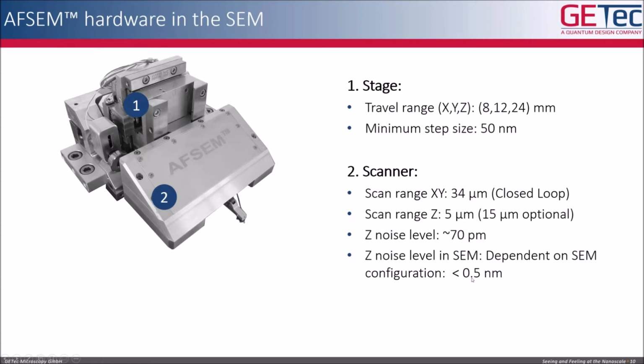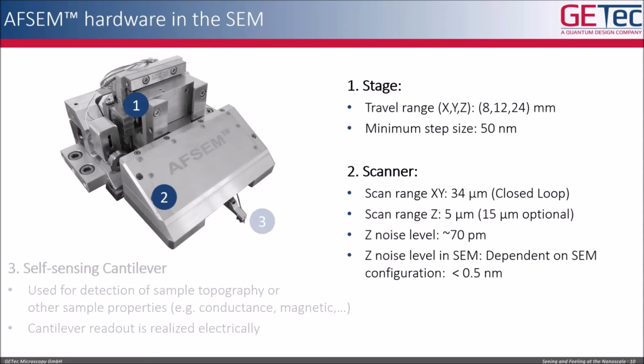it is, of course, highly dependent on the SEM configuration and the vibration and noise level in your specific SEM or dual beam system. But even for older SEM systems, we always managed a noise level below 0.5 nanometers, which gives you this atomic resolution in Z.